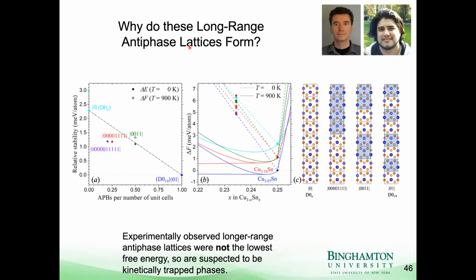Why do these long-range antiphase superlattices form? That's one of the questions that we had, and it hasn't been addressed in the literature. Ernesto did some simulations of different periodicities. They were limited because DFT is a very computationally intense calculation. So they did a case of no superlattices, a superlattice every 4 unit cells, a superlattice every 2 unit cells, and a superlattice every unit cell. And they found something surprising.